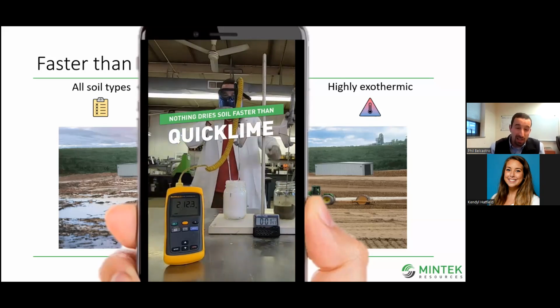And you can see the timer there. That took about 1 minute and 40 seconds. But really it was only about 15, 20 seconds of action with the quicklime there to absorb that water. So pretty impressive what it can do. Maybe a quick caveat there. In the field, we're obviously adding it in more of a controlled manner, so that's not what we're going to see. It was just a little experiment to show us what we can really see.